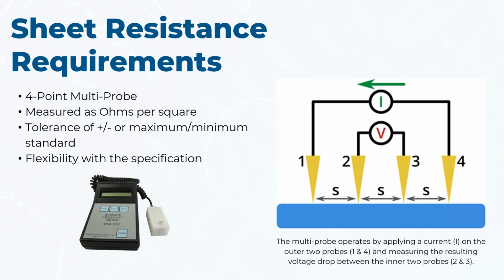There is some subjectivity on maximum and minimum requirements. If you specify a maximum, but you don't give a minimum, then you could get a very, very conductive coating and not intend to. And the inverse is true. If you specify a minimum resistance requirement, you can get a very minimally resistive coating and not intend to. So usually a plus or minus tolerance is your best practice, but maximum and minimum come into play pretty often. And if you know that you can afford lower sheet resistance than higher, specifying a maximum can make sense. And this is actually a picture of a 4-point probe here. This is very similar to the one we use internally.